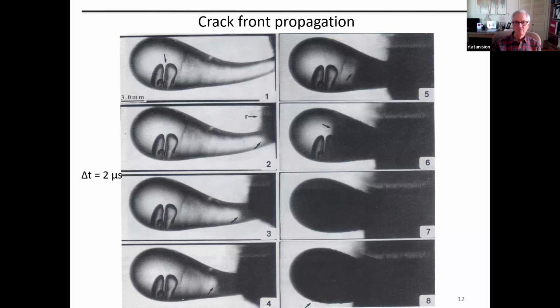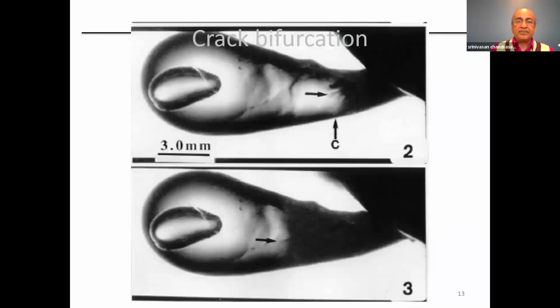So crack velocity is about 1700 meters per second, the peak velocity of the crack front, and it propagates from the tail to the head, and eventually the drop disintegrates. But now let's see if we can get some more detail so that we can explain what the mechanism of disintegration is.